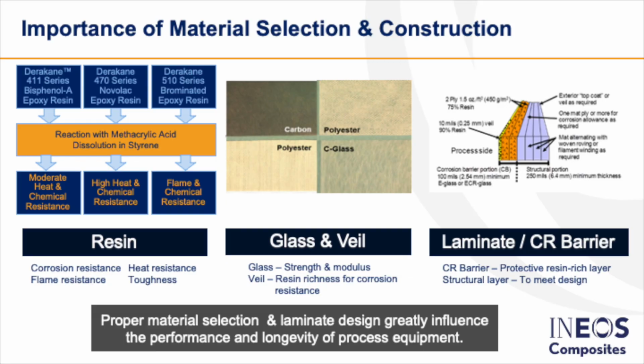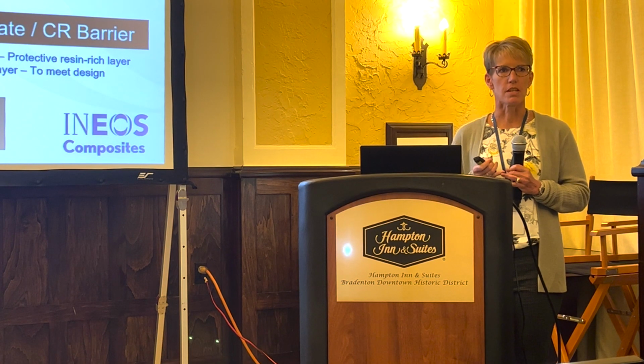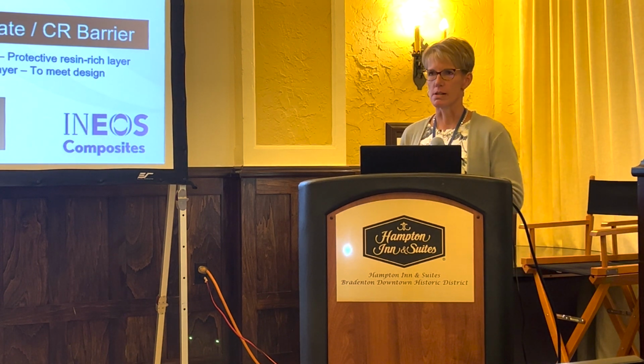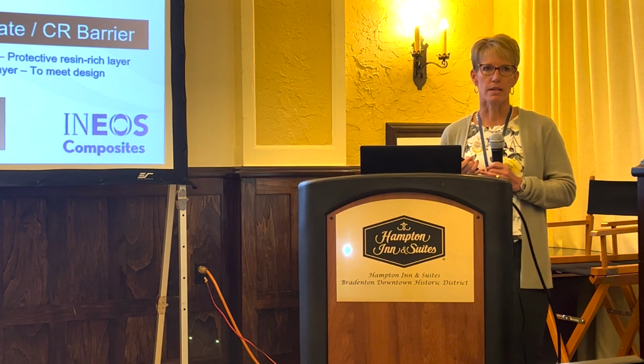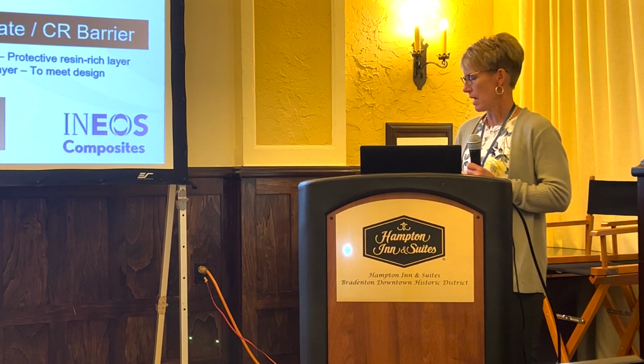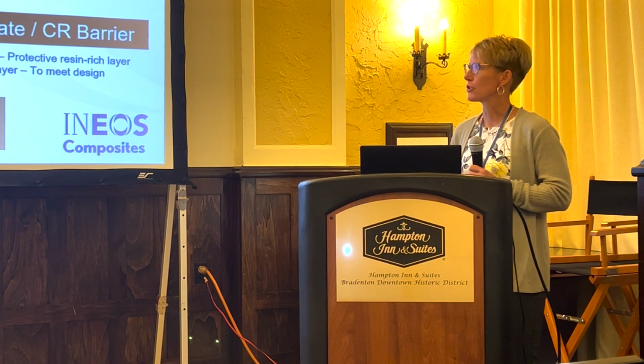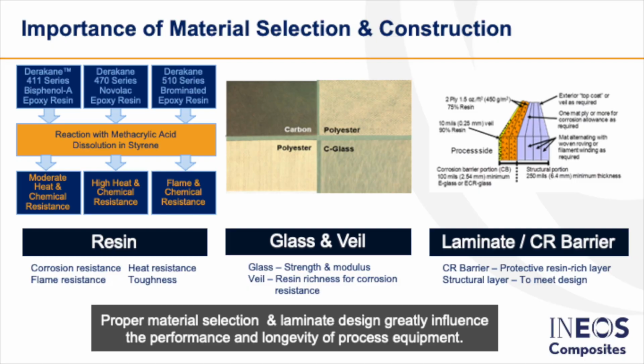So over here, just a brief summary of some of the different types of epoxy vinyl ester resins that you will commonly see. What we call the Derakane 411 series is a bisphenol A vinyl ester resin. It's going to have excellent temperature resistance and overall good resistance to acids and bases. And then your Derakane 470 series is a Novolac epoxy vinyl ester. That will also see excellent resistance to acids, not so recommended in caustic environments, but also excellent solvent resistance and temperature resistance. And then for the applications where you need that good corrosion resistance as well as flame retardancy, the Derakane 510 series, which is a brominated vinyl ester resin.